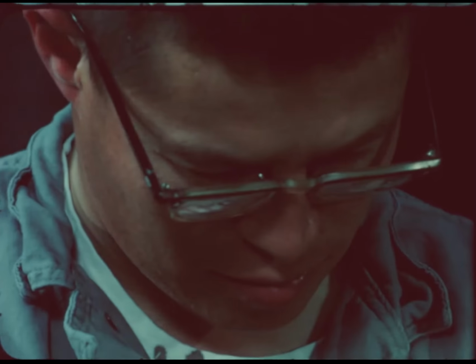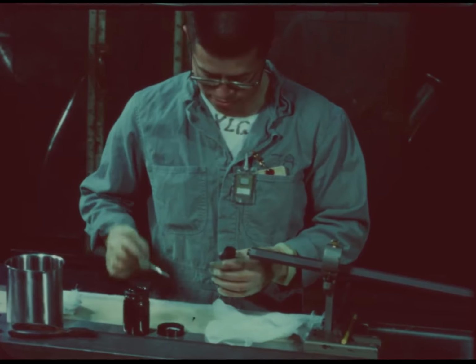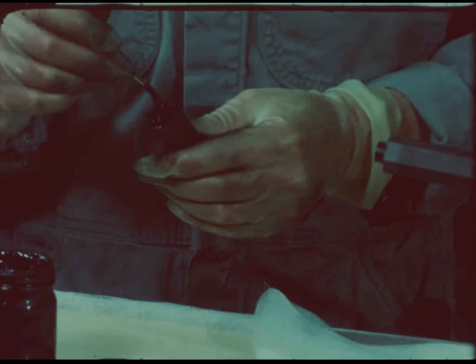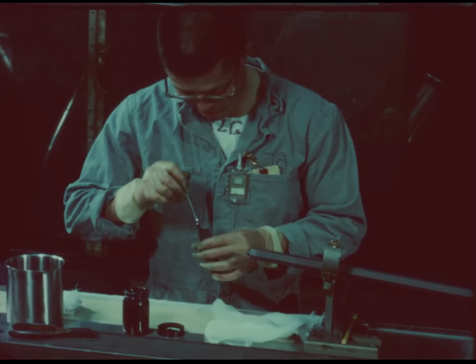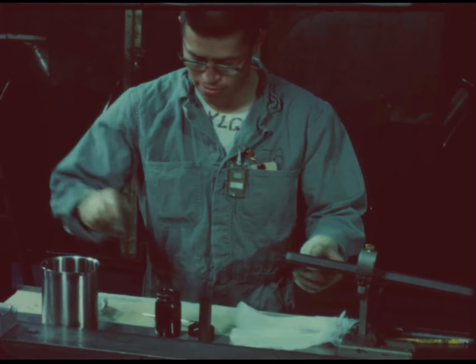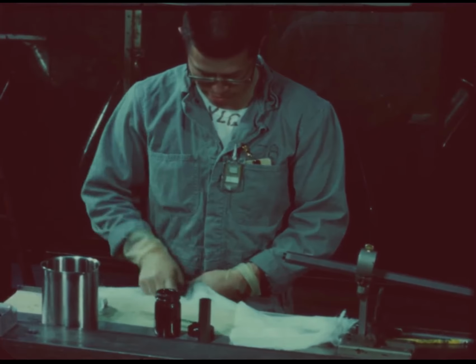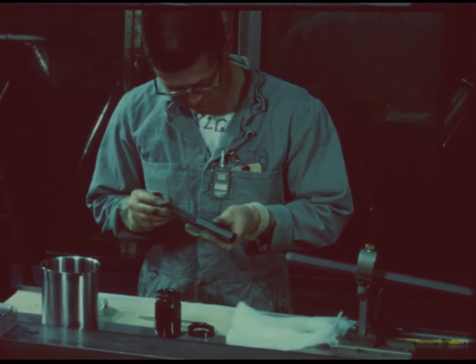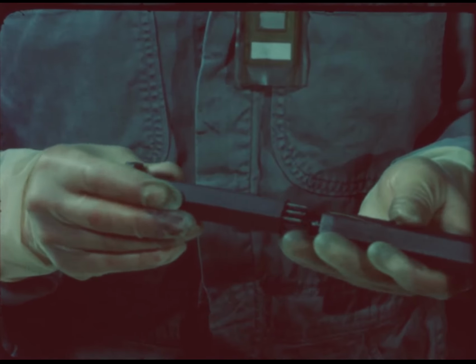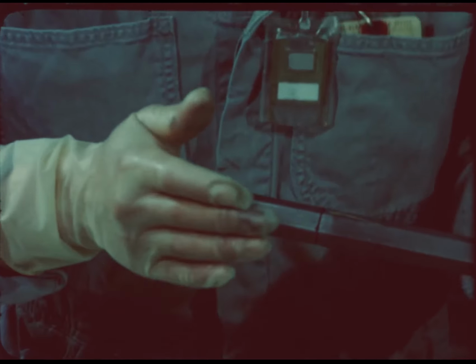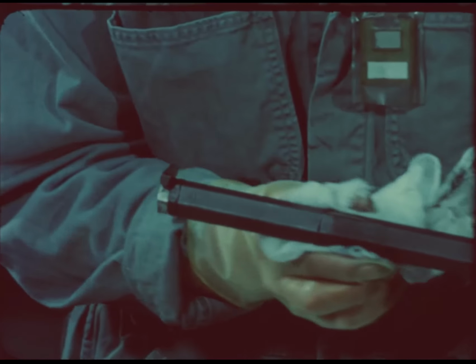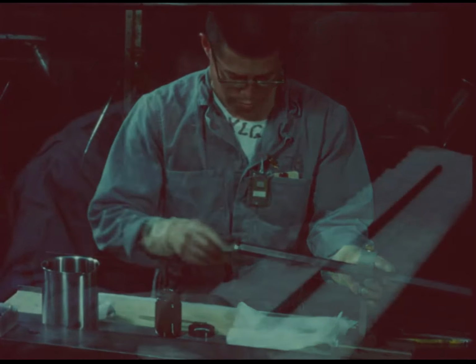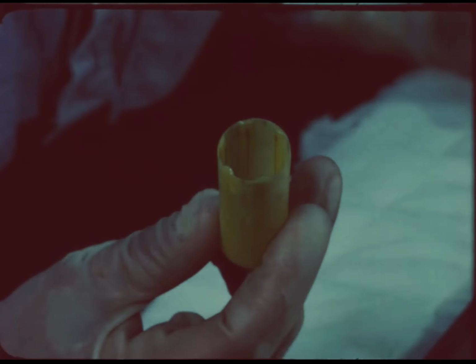Because the coating does adhere better to unloaded graphite, it was decided to glue an unloaded end to a loaded element before coating. This procedure proved to be extremely effective, and use of these elements during full power runs has shown that the glued ends remain in position. Another recent development is this protective cap used to guard the coated end of the element against damage.